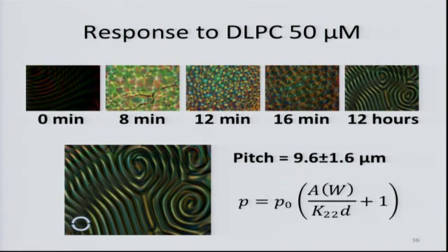And we know that the pitch of the cholesteric liquid crystal, when it's under planar alignment, has an intrinsic pitch of maybe 5 micron. But when we do these fingerprint textures, while having this vertical alignment, we see different periodicities. And when we use different surfactants, those periodicities change.